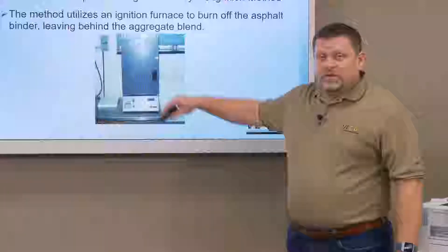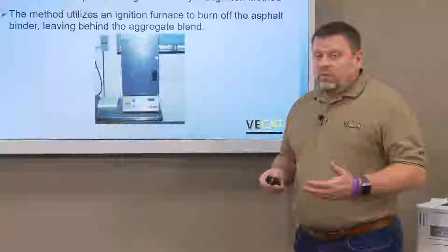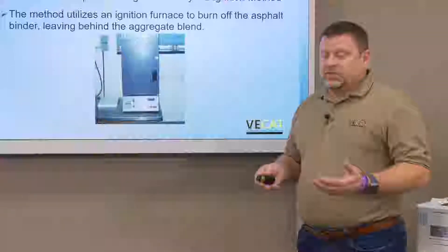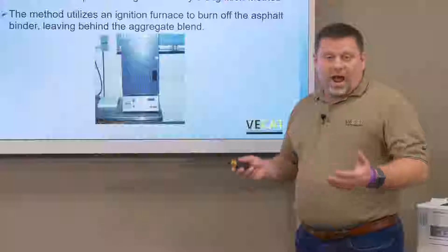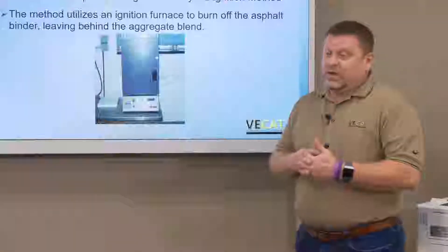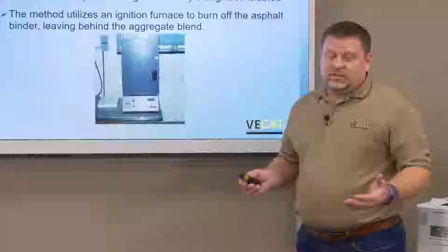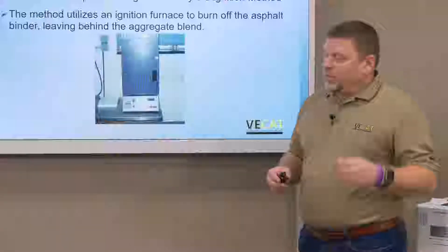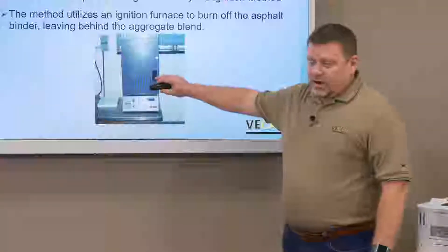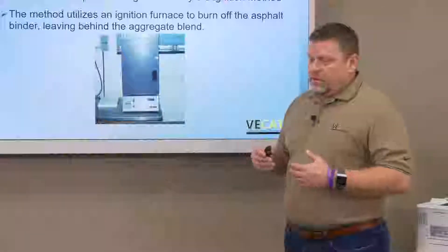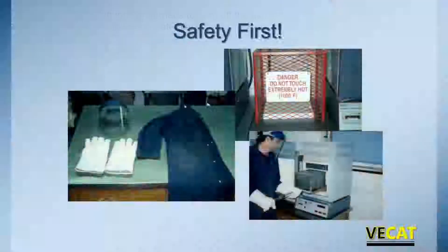The nice thing about using the furnace is I can get an asphalt content in an hour or less. With the old reflux method, it could take four hours, or in some cases when dealing with high binder contents, whole days to get an asphalt content on one sample. This is a much quicker way to measure asphalt content, which is a huge benefit to the asphalt producer when he's trying to control his mix.